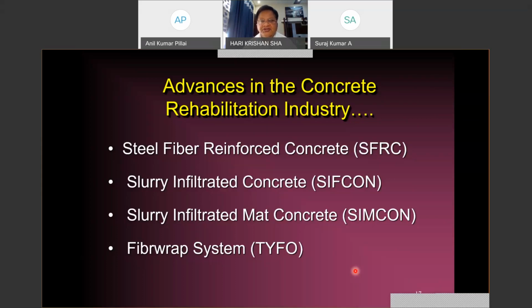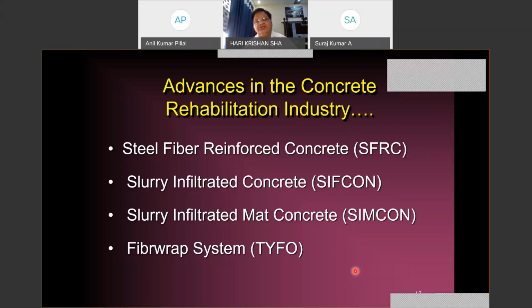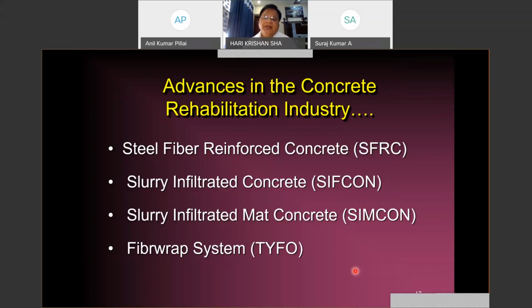In SFRC, we mix the steel fibers in the concrete itself. Whereas in SIFCON, the steel fibers were laid in the mold, and then cement slurry was filled in and compacted. By this technology, you will be able to increase the fiber content up to 20% by volume of concrete, and there will be a tremendous increase in flexural strength, compressive strength, tensile strength, and so on. This methodology was also used for rehabilitation or retrofitting of these structures.